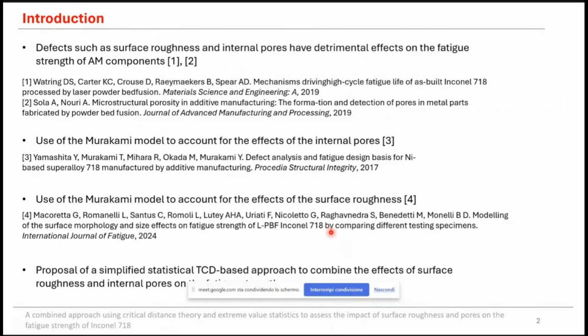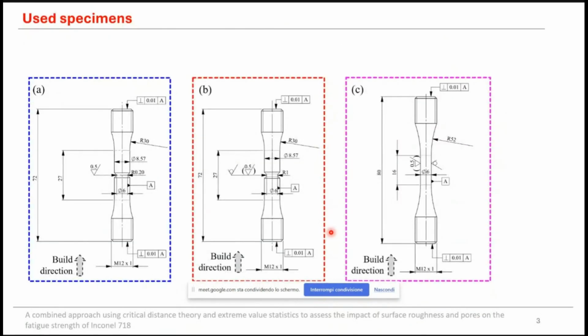In this work, we proposed a simplified approach combining the theory of critical distances and statistics to describe the combined effect of porosities and surface roughness on the fatigue strength of AM components made of Inconel 718 under different surface conditions. The specimens that were manufactured in this research are presented in this slide.